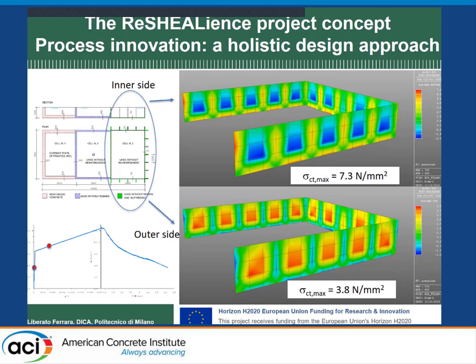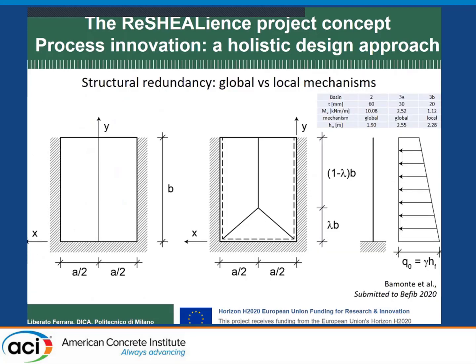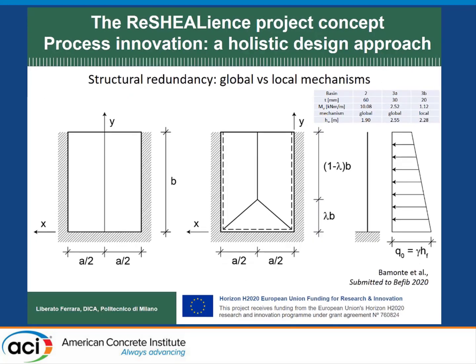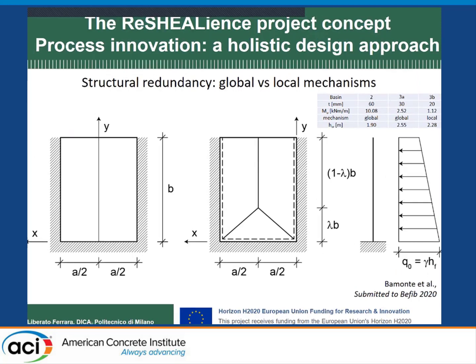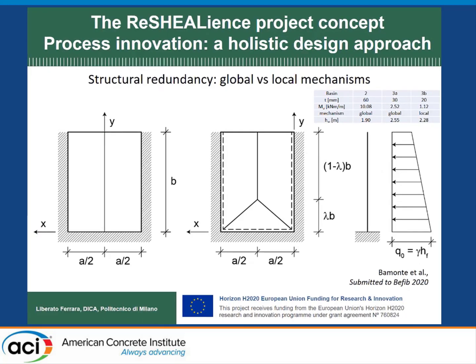Well, actually, this is a slab. This is a statically redundant structure. So we also made a yield line analysis and found that, since the basin has a depth of 1.5 meters, it could actually withstand an overload up to about 2.3, 2.5 meters. So from the structural point of view, we were quite safe.